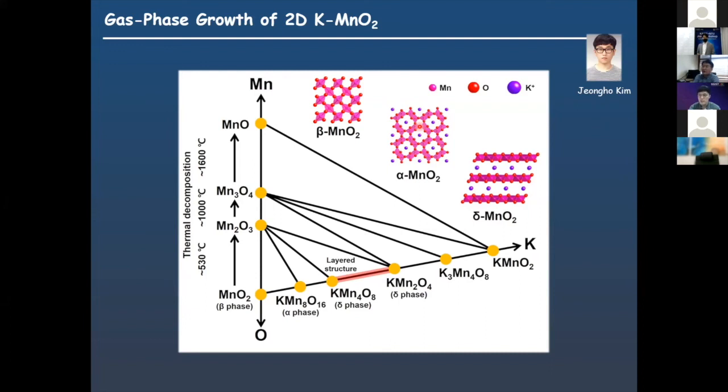That's my general question about oxide 2D materials. In the manganese oxide case, it looks like there's definitely some stable 2D phase. But tungsten oxide is known to have very stable 2D phases. So the only difficulty is the exfoliation, not the material itself. That's what I know. Molybdenum trioxide is obviously a layered structure. Maybe in the tungsten case I don't know. I see. So there are certain phases of 2D oxides, but the exfoliation is more difficult. Yeah, exactly.